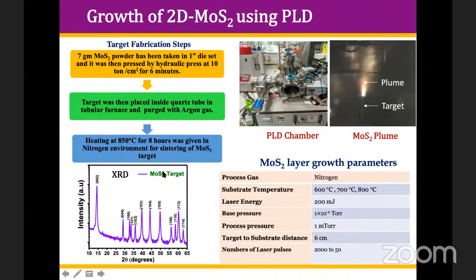so that the densification is there. And this is the XRD of the target, just to ensure that the target is pure, there is no other impurity present. And this is well indexed with the literature, which confirms that the target is MoS2. So this target has been used in the system with these processing conditions.